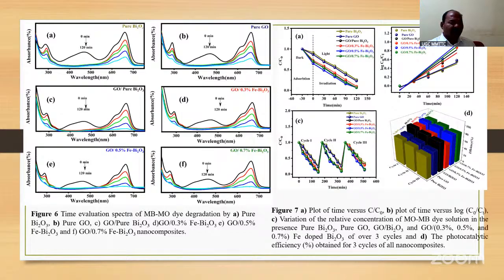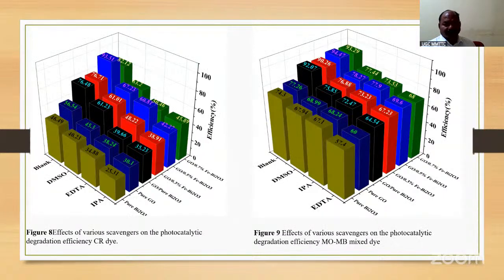So this is the work carried out in the laboratories using different dyes, that is methylene blue, then the MO, and then the MB. The effects of various scavengers on the photocatalytic degradation efficiency are shown here, in this percentage. Now you see this enhanced with different scavengers again. For this, 0.7 GO and 0.7% iron, it is highest, and for pure it decreased. Now these are the cases here.